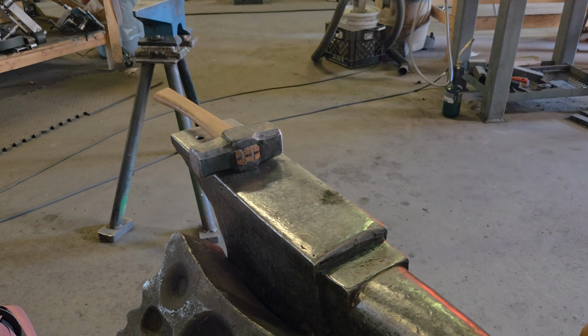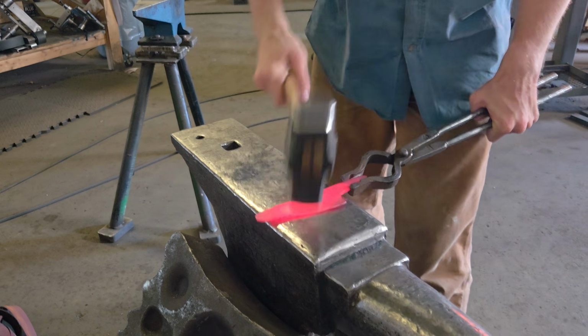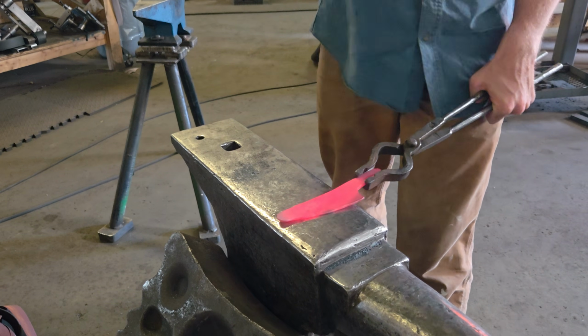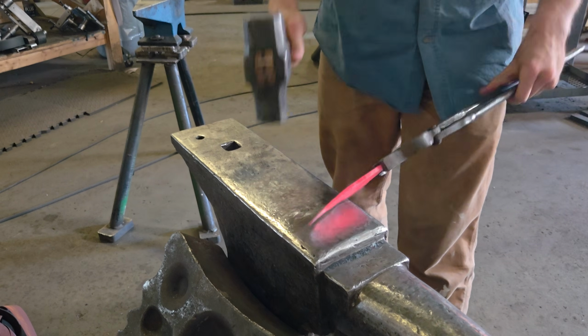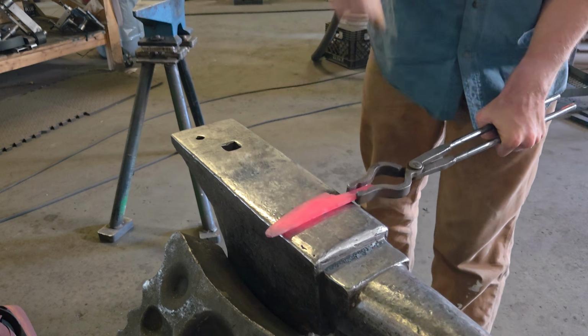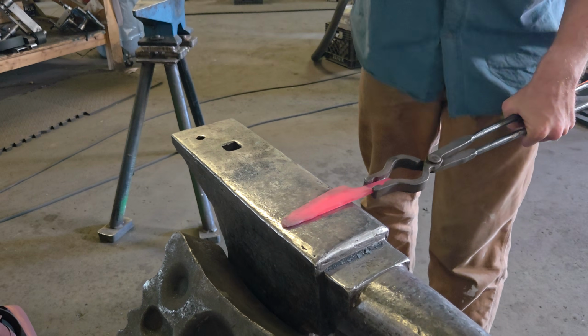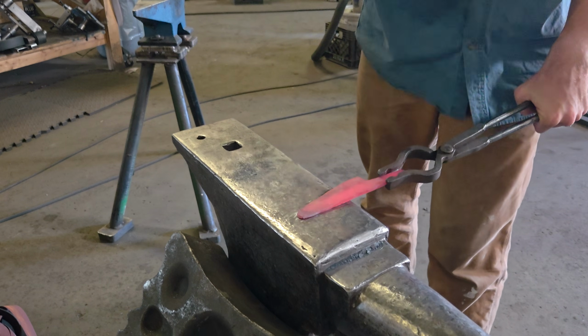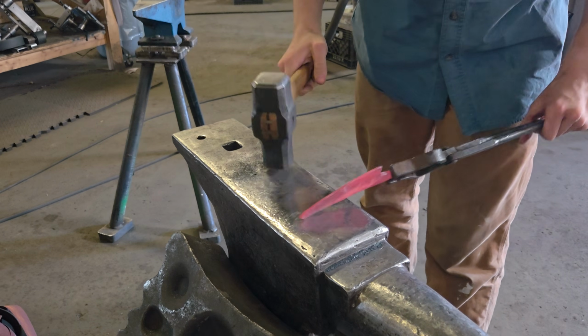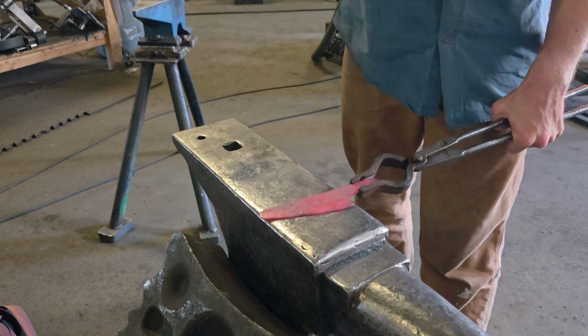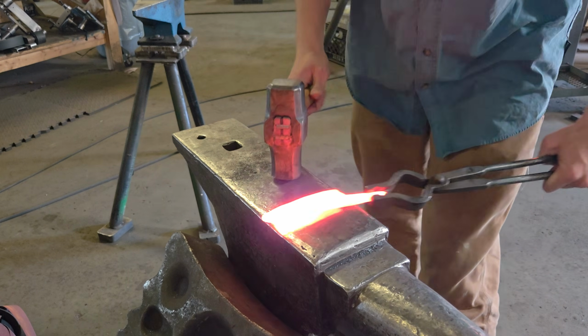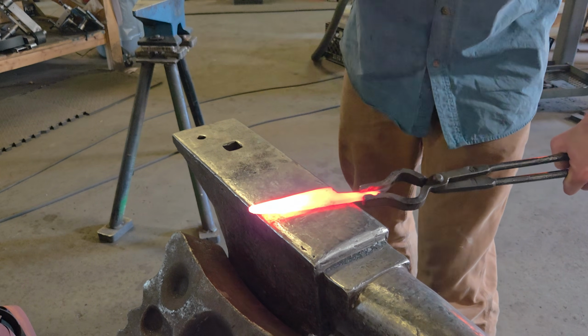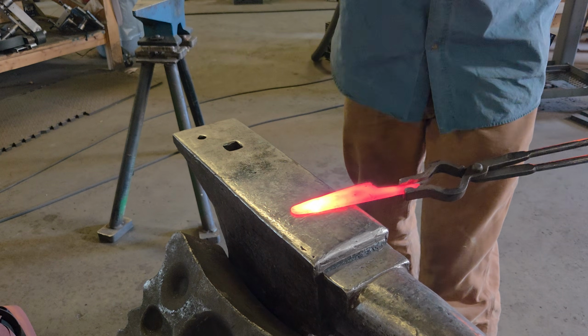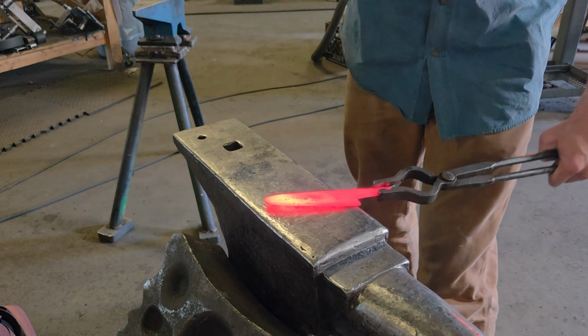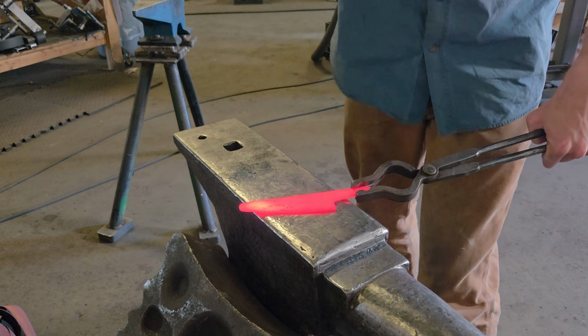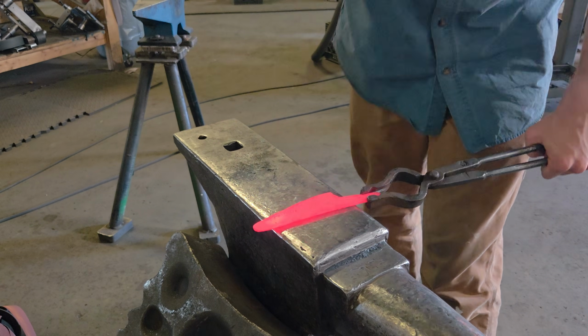Drop forged again. As you forge the flats of the blade, everything gets thinner, which makes the material move less and less. Also, as the blade gets thinner, it cools a lot faster on the surface of the anvil. So these are all the things you want to be aware of as you're forging the flats, because you've got to really watch your temperature, and it really starts to move less and less as it gets thinner. So you got to hit really hard to make this stage go by faster. Don't hit too hard as it gets cold though, because it can crack your steel, so be careful.